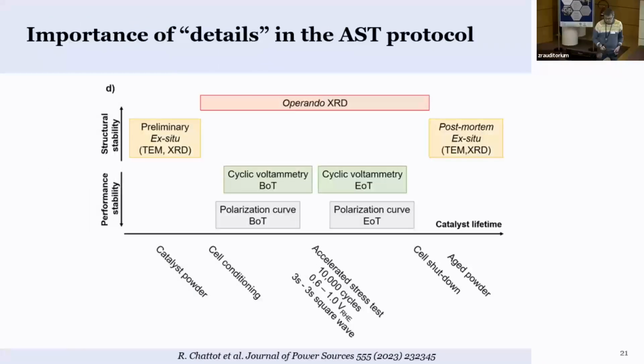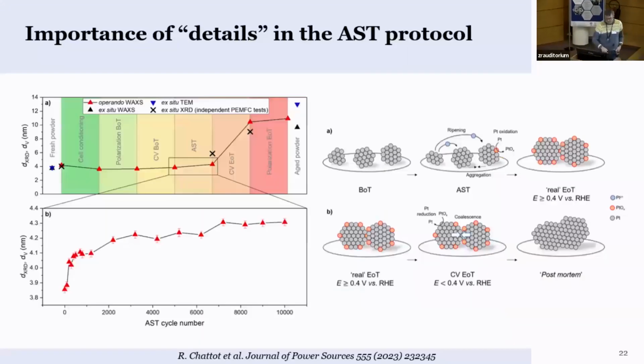And then some work here from the IE31, where they looked at the different stages of such a protocol. And it turned out that it's actually these fine details. Everyone uses more or less the same protocol, but it's what you do in between. So for us, establishing the surface area is very important, because that's a value you would like to have also during or in between the measurements. And what they could show is that this actually is not always a good idea.